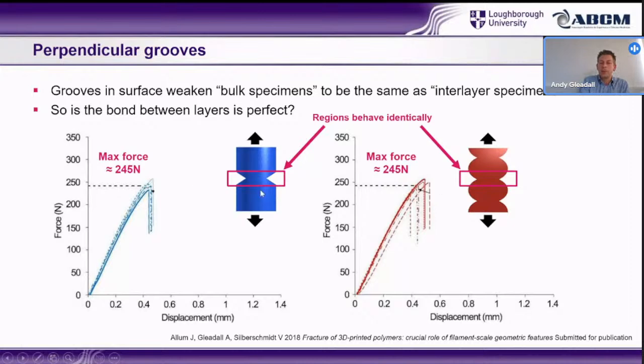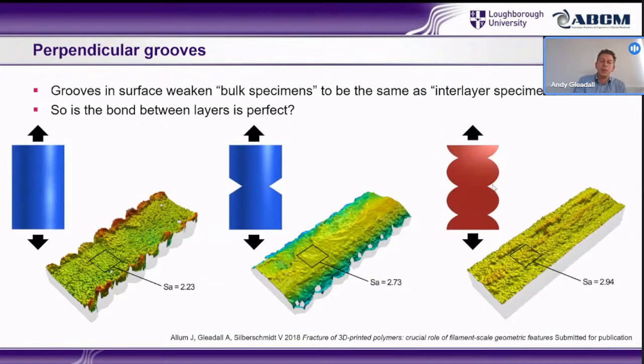The properties of the solid polymer just matched that of the polymer that was tested in the Z direction, or between the interlayers. So it's suggesting that actually the bond is perfect, and it's just the geometry that needs to be considered. Now we back this up with really detailed analysis of the fracture surface, which is again only really possible because we've taken it from this large complex toolpath for tensile testing specimens to these very simple ones.